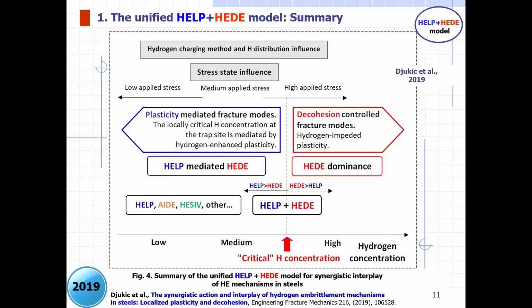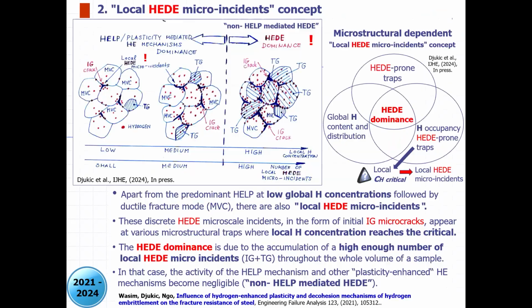And after that, it sharply decreases, and that transition is more important. So in the case of HELP predominance, we have so-called hydrogen-enhanced plasticity of the material, and we must carefully investigate when that happens in our material.